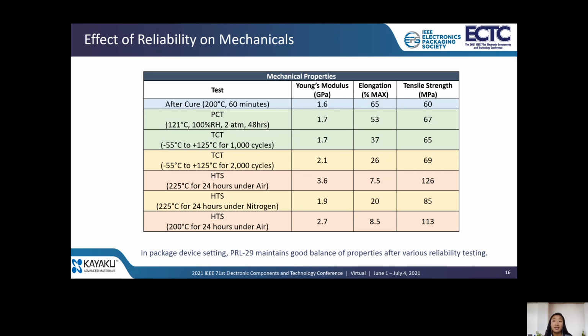High temperature stability testing is extremely harsh conditions, and we see after 225 degrees C and 200 degrees C for 24 hours of testing under air, the material does become more brittle, and this is really a result of PRL-29's oxidative stability. However, the material will likely be in a sealed package, unexposed to air, so to simulate this in-package environment, we ran the test under nitrogen. As seen in this table, the material properties do not begin to degrade as they do under air.